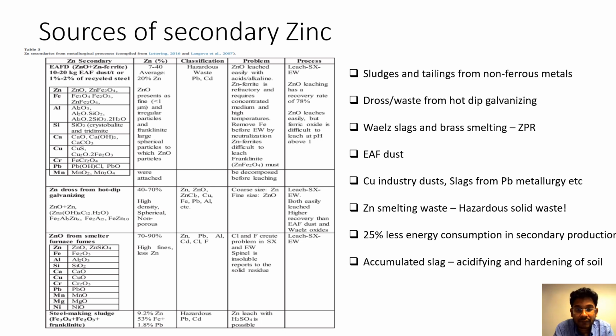And you also have, let's say, the existence of halides, especially from the smelter furnace fumes. The halides could create a problem in both solvent extraction and electrowinning. And yeah, so basically the key thing that you have to understand from here is that the EAF dust and the dross are two of the most important resources. And zinc accumulation and slag landfilling have environmental issues associated with them, which means it's imperative to recycle it, at least from the ecological perspective.